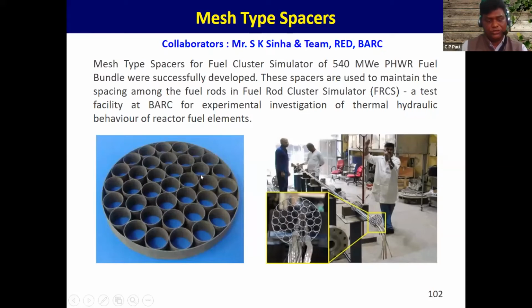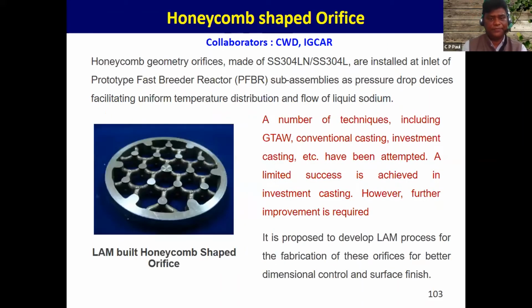They used to do this job with EDM wire cut, and it used to take 7 working days to build one component. When we took it to our powder bed fusion machine and built the same shape, to our surprise, the fabrication time came down to 2.5 hours. So you see, 7 days converting into 2.5 hours. And this is the change additive manufacturing is bringing.